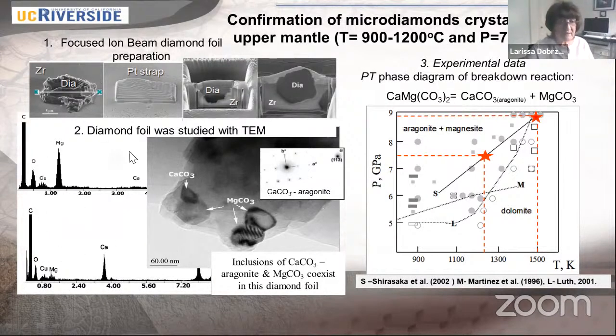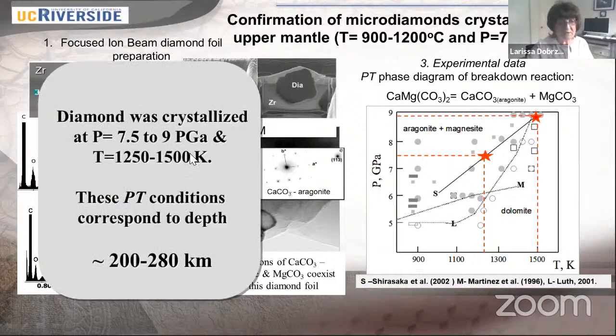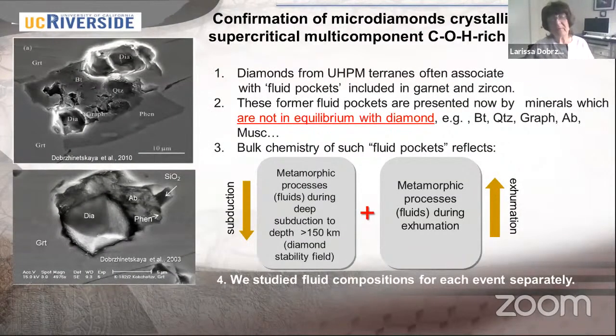Okay, so when we know all this data from TEM studies, then we go to search experimental setups. And we found a lot of experimental data, which show the pressure-temperature phase diagram of the breakdown reaction of calcium magnesium CO3 with production of aragonite and magnesite. So we determined that for this particular diamond, the crystallization pressure was between 7.5 to 9 GPa, and temperature was 1,250 to 1,500 K. So these conditions correspond to a depth of about 200 to 280 kilometers. So we learn a lot about this diamond.